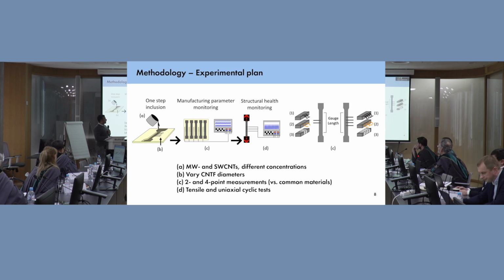There is a possibility, because I don't believe that it is, we assume, of course, that the piezoresistive response is uniform throughout this area that we're monitoring from the nanocomposite. However, the percolation network could be just better at the surface. So in this case, the response might be primarily from there or primarily from the volume, depending upon where it is. It's a technical question from the data that we have. I cannot tell you exactly. Do I think that theoretically it's possible? Yes.